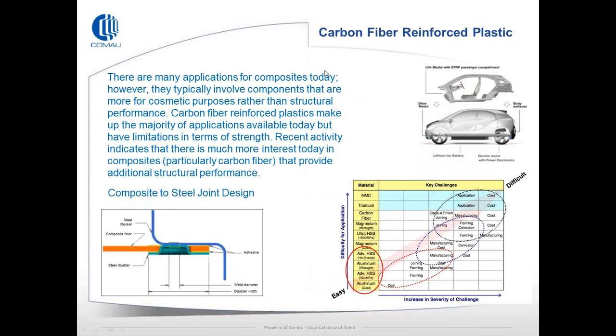We mentioned earlier in the presentation about carbon fibre, and the reason for this slide is to discuss carbon fibre and its introduction, which is, let's say, more cosmetic historically, but now becoming more commonplace as a production medium and also integrating into the high volume. What this is showing is that by utilising good design, multi-material and multi-processes can come together. So here, for example, we've got a composite floor, and we've got a steel top and bottom section. As you can see, the lower section has a depression in it, which allows the top and bottom material to be joined, which in this instance is showing a resistance weld spot, but could be a self-pierce rivet spot.